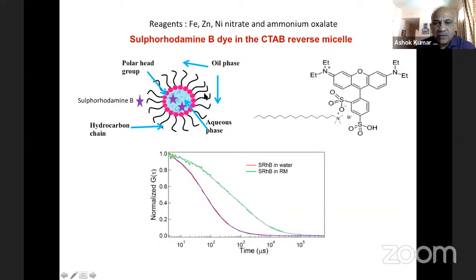So what you see, this is an example. So this is a droplet. These are our surfactant molecules, and inside we have this nanoparticle growing, or it is a bare droplet, that means no nanoparticle. And you put a dye, here it is sulforhodamine dye, which is negatively charged, and it sits close to the positively charged head group of the surfactant, which is CTAB. So the dye, when it fluoresces, you know what is happening at the interface, and when this reverse micellar droplet with the dye is moving, you are looking at the fluorescence, and the fluorescence intensity you can mathematically model, and you can get the numbers which I showed in the previous slide.